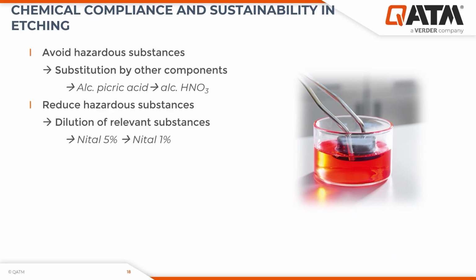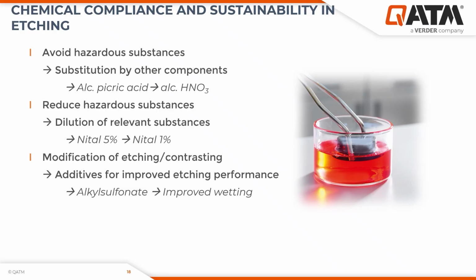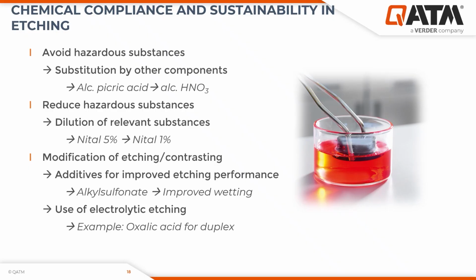Additionally, you can try to modify your way of etching by adding additives for improved etching performance, which is usually done by the manufacturer of the etching agent and not necessarily in your lab. You can try to add alkyl sulfonates for improved wetting performance, so basically improving the overall etching performance of your etching system. And you can also try to exchange the classic chemical etching with electrolytic etching. For example, you can perfectly etch duplex steels with the use of oxalic acid and exchange your etching process completely.